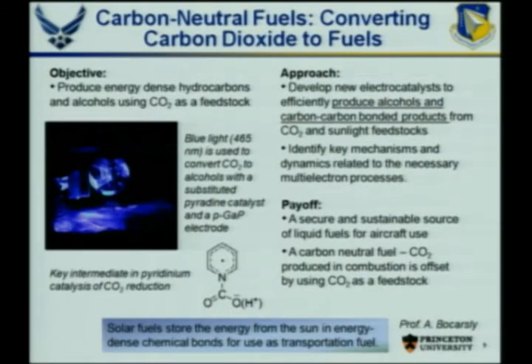Sometimes there are substitutions of pyridine, where you put some different binding groups on there. So the mechanism of this is not very well understood at all, and that's going to be one of the challenges that we're looking at, is to try to understand how the electrodes and the catalysts play a role. One of the most important steps in this, the first step in getting this to go, is binding of CO2 to this nitrogen in pyridinium. So you get this CO2 bound to this. That's postulated in their mechanism.